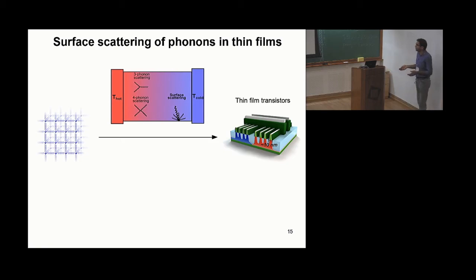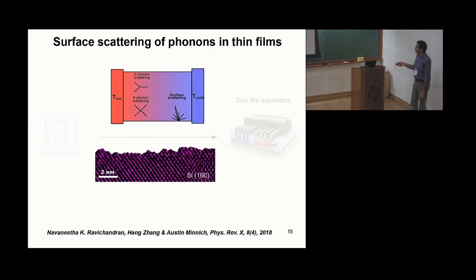And this scattering process of phonons also adds to the thermal resistance, but it is not well understood in literature. So that's basically what I wanted to do: take a thin film, and find out the rate at which phonons scatter at the surface and its manifestation on thermal conductivity at a more microscopic, phonon mode resolved level.